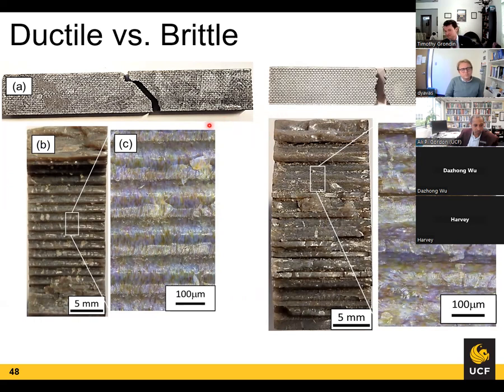First telltale sign is going to be the break. So we've got the flat printed sample on the left and the vertically printed sample on the right, printer orientation wise. In the left sample, you can see immediately once it gets past the face sheet, it beelines at a 45, almost textbook ductile breaking. Whereas on the right side, our fracture is 90 degrees.